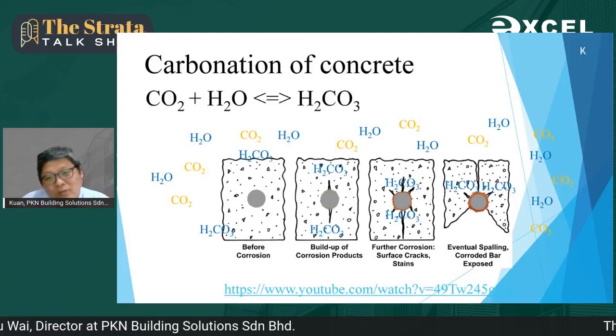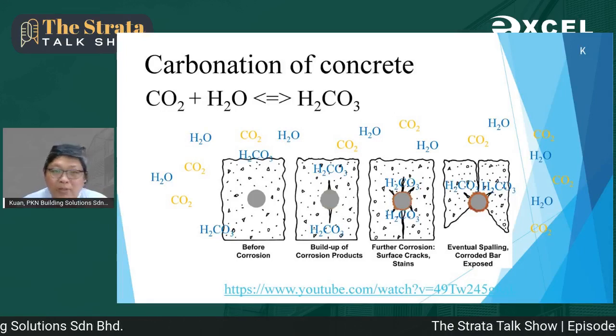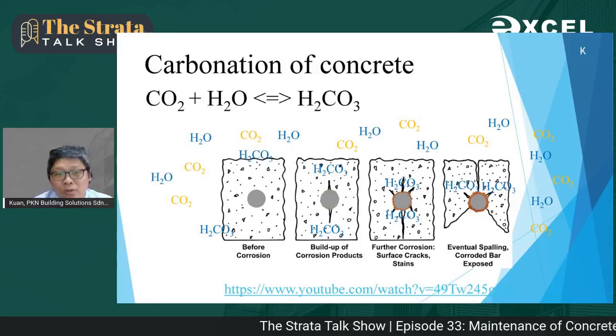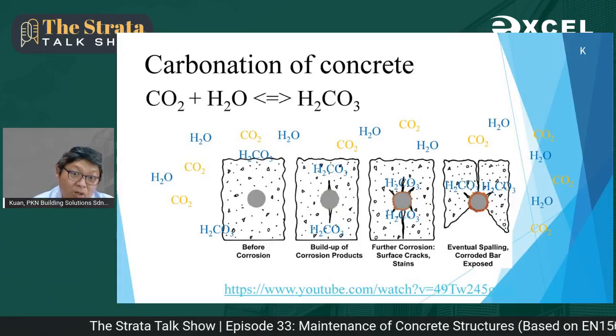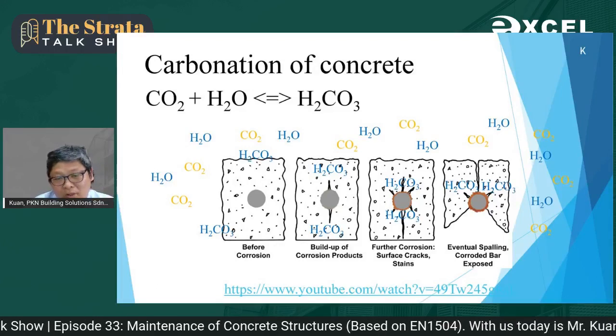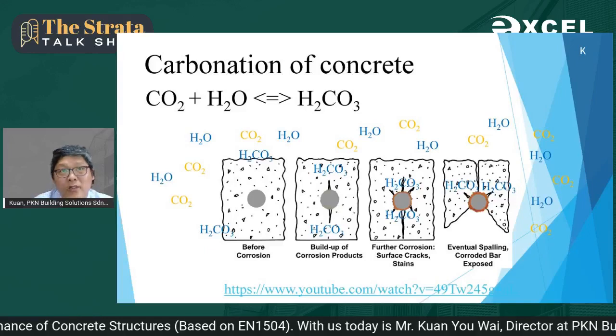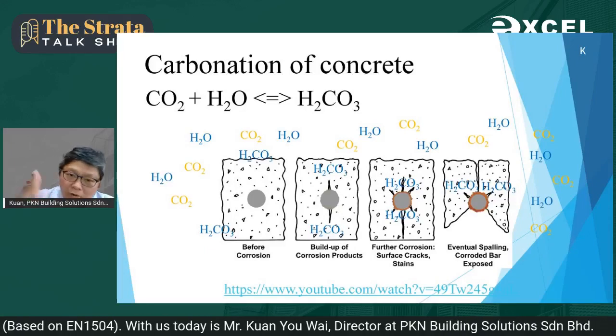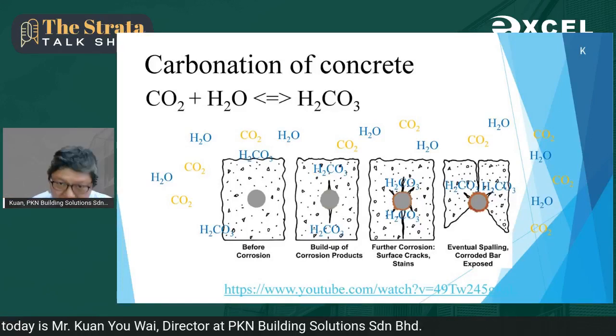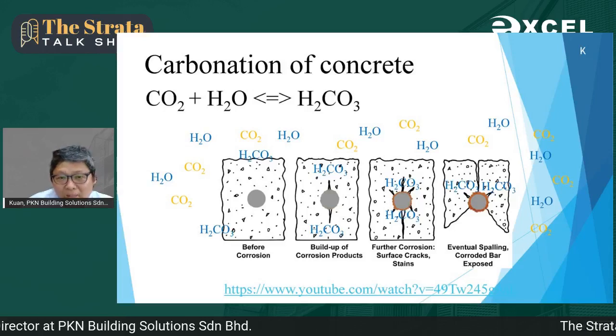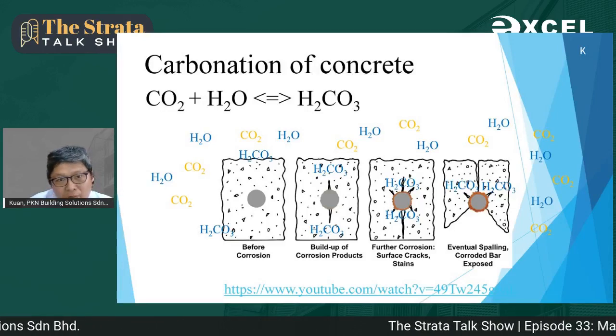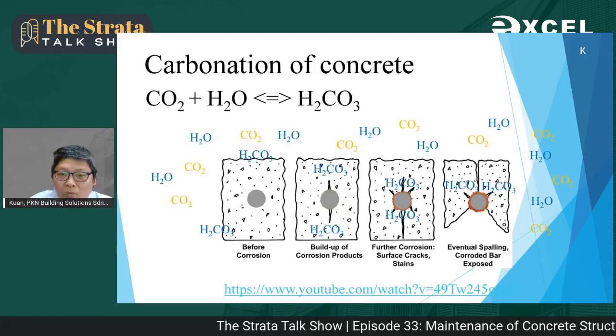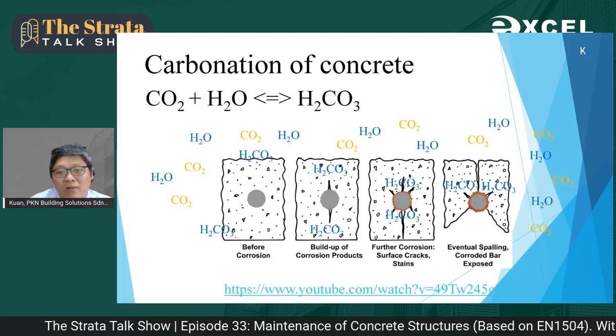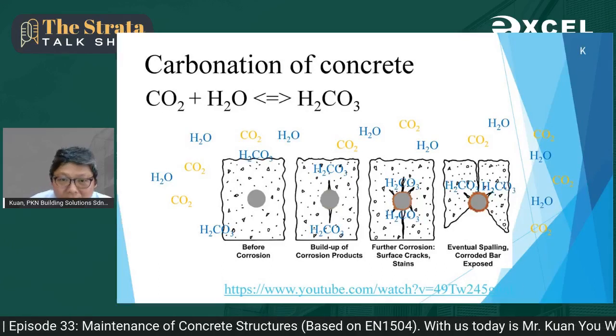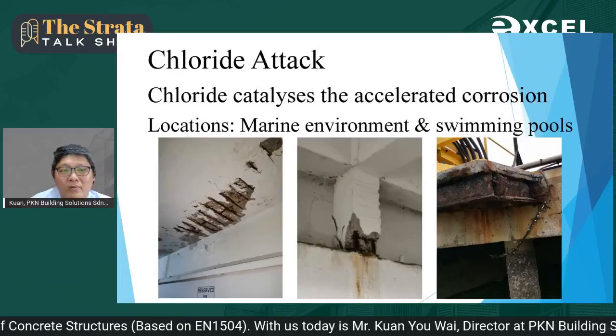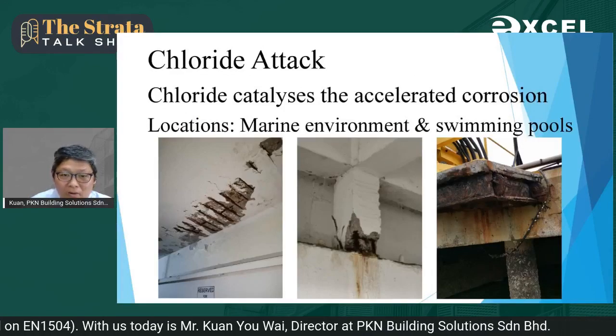And carbonation is one of the major causes of corrosion. Okay, our rainwater, upon exposure to carbon dioxide, will form carbonic acid. Carbonic acid will neutralize the concrete. The original pH of concrete is 12 to 13. It can bring down the pH of concrete lower and lower. When the carbonic acid neutralizes the concrete to a pH of 9 and reaches the reinforcement steel bar, then the corrosion will start. It will crack the concrete from inside, and eventually you will see something like this.